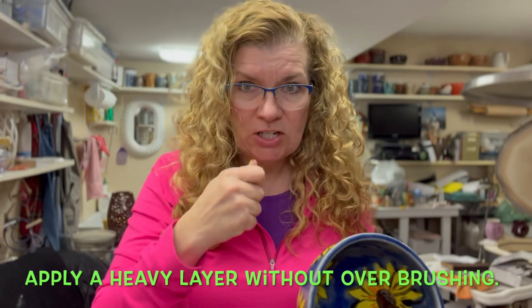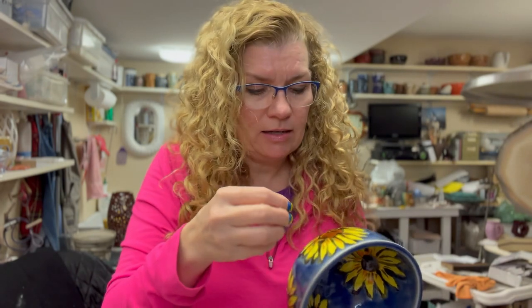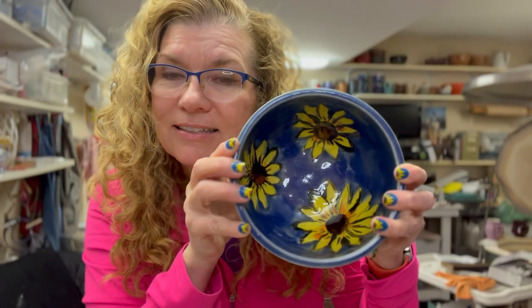One other tip when reapplying glaze: because the surface has already been sealed by the first glaze firing, it's not going to dry and soak into the clay body like it would on a bisque piece. It's not easy to put on multiple layers — each layer takes a long time to dry. I also wouldn't brush a layer on, let it dry, then brush another layer over it because you can really pull it off. I try to blob it on a little bit thicker instead, applying it heavier rather than brushing traditionally. Hopefully you find these tips helpful — drop any questions below and don't forget to subscribe.